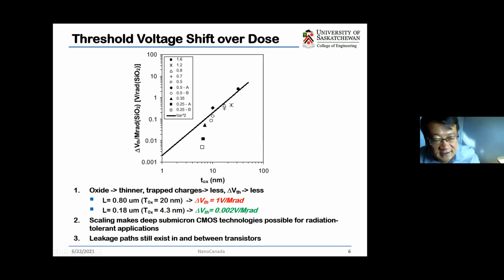So basically, it indicates that this technology is scaling, right? And then deep submicron, nano CMOS technology has become possible for radiation tolerant applications. This explains why nowadays we can start to use commercial CMOS technology for space and many other radiation applications, just because this total dose effect has been greatly reduced. Of course, the leakage path still exists between and inside the transistors because of the oxide, but it is relatively much less significant compared to the older technologies.